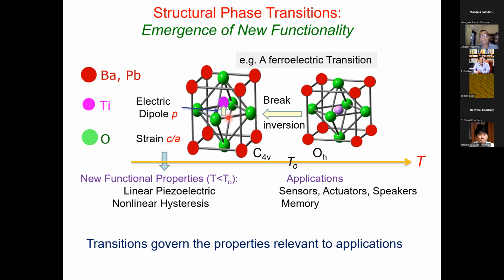And once a positive ion gets off-centered with respect to the negative oxygen ion, you develop an electric dipole moment below the transition temperature. And the symmetry allows this dipole moment naturally to distort the crystalline lattice to a tetragonal shape, giving strain as reflected in a non-trivial c/a ratio.